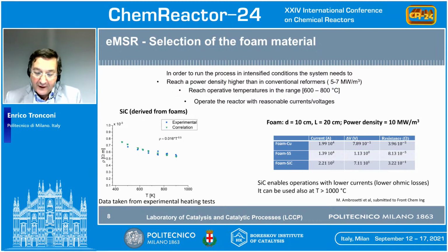On the other hand, we found from our preliminary heating tests that silicon carbide foams or honeycombs actually exhibit optimal electrical resistances. And this is not surprising because silicon carbide is used for the manufacturing of commercial heating elements in electrically heated furnaces, for example. And silicon carbide is also very interesting in view of its excellent thermal conductivity, which is much higher than stainless steel.